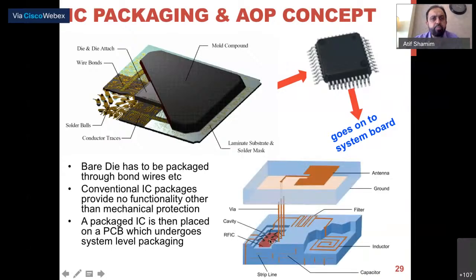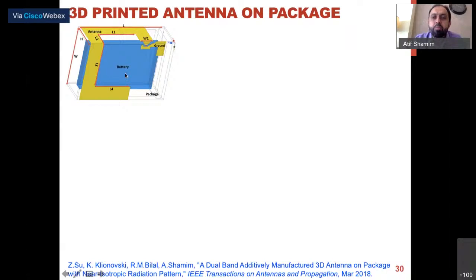So this is a work where we've designed an antenna on package. You could see the battery in the model and the electronics is inside the package. The package has been 3D printed. And this is a GSM antenna which is supposed to work on both bands. And one additional thing which we were trying to do was, because this was for an IoT application, we wanted a kind of a near isotropic pattern. So whatever is the orientation of this package, whatever is the orientation of this box, we should have some coverage. We should have some radiation. So we wanted a near isotropic pattern.